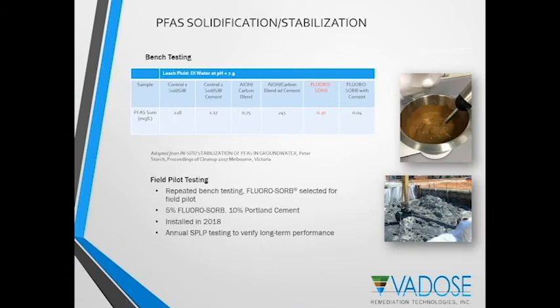So going on to some work that has been done on FluoroZorb, this first study was by Peter Storch of Arcadis in Australia, presented at the proceedings of a cleanup conference in Melbourne, Australia in 2017. And essentially what we have here is some leaching testing that was done first on the control sample, which had a 2.28 milligrams per liter leaching of total PFAS compounds. The second control, when stabilized with cement, that number was reduced to 1.17 milligrams per liter. A proprietary blend of aluminum hydroxide and carbon was added as an alternative and was able to reduce the leaching to 0.75.